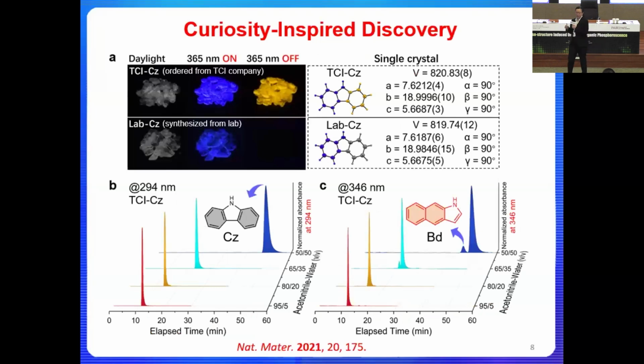Now, let me use carbazole, the initial original material, as an example. We can get these molecules from a lot of commercial sources, and we can also synthesize them in the laboratory. So the key difference is the phosphorescence phenomenon. If it's from commercial sources, you will be able to see this bright yellow emission after the light illumination is removed. But if we get the pure molecule, this phenomenon disappears.